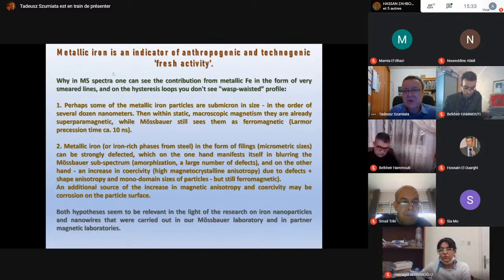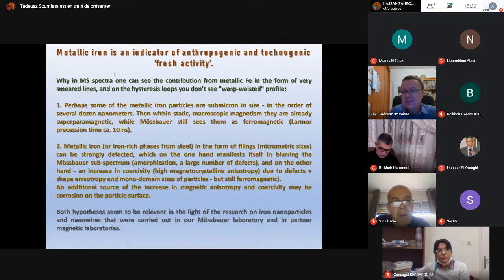Probably the problem is in the size of the grains. As I mentioned, we rather expect very small particles of metallic iron. So maybe they are just superparamagnetic from the macroscopic point of view. In the Mössbauer, they are still visible because Mössbauer is very fast, a 10 nanosecond probe. It is a characteristic Larmor precession time. Yes, but in the case of just static magnetism, there is nothing at room temperature.